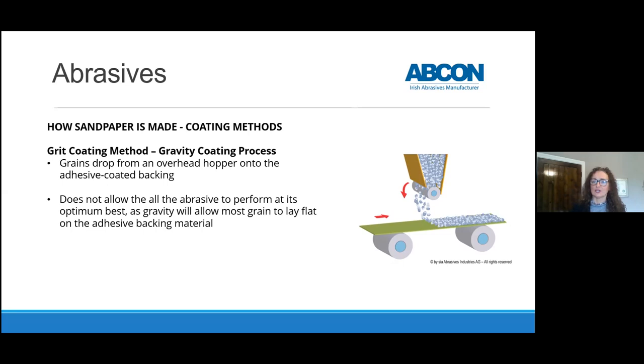And then the other element is your abrasive grain, the mineral that's applied to it. So in the gravity coating process, the material will roll underneath a hopper, and the hopper will release the grain on top of the adhesive material. Now, the problem with this is that all of the abrasive may not perform at its best, because gravity will mean that some of the grain will be allowed to lay flat on the material. So basically, the sharpest edge may not be exposed.